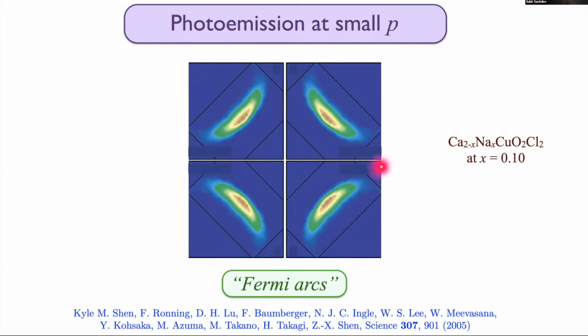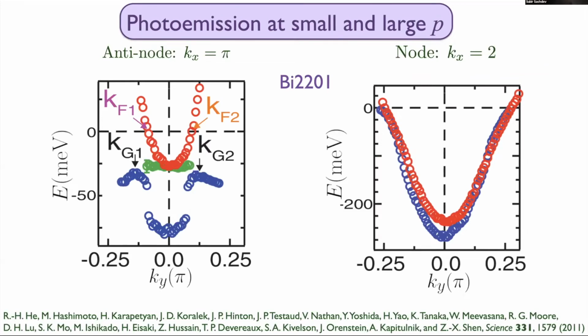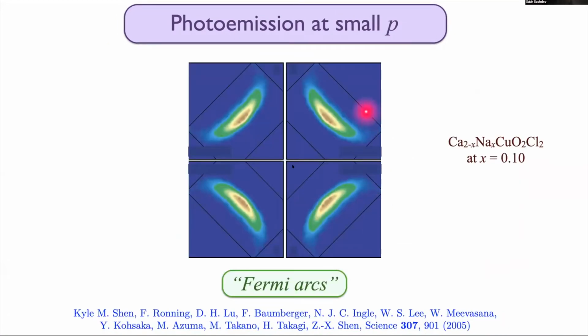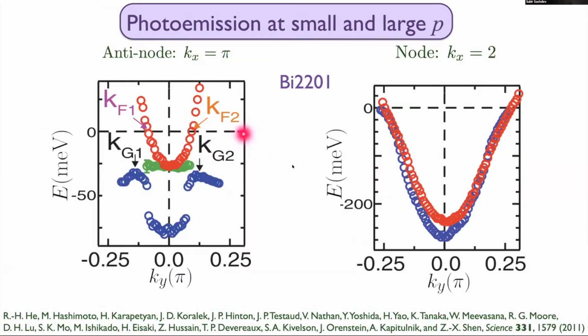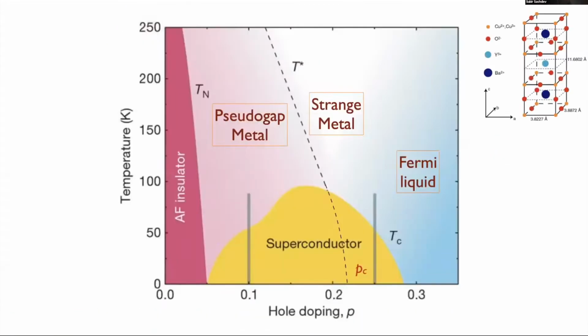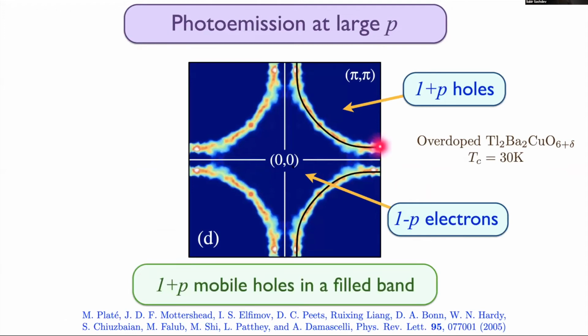Now, since then, of course, this has been looked at much more carefully. In particular, I want to focus on the high energy excitations here along the antinodes. So this is another famous paper by ZX Shen's group showing you these excitations in that regime. So what do we have here? So they're actually lowering the temperature, but at higher temperatures, before you enter the pseudo gap, you have this dispersion here, which, so as you go along this axis, you are moving along this axis over here. And this zero crossing here, which you see in the overdoped side and also at higher temperatures and underdoped side, that zero crossing there is not here, it's here. So that zero crossing are these 2 points here.